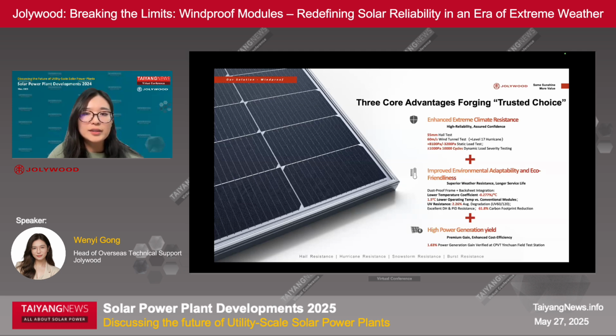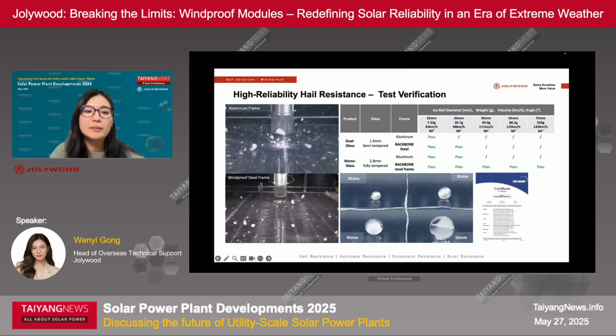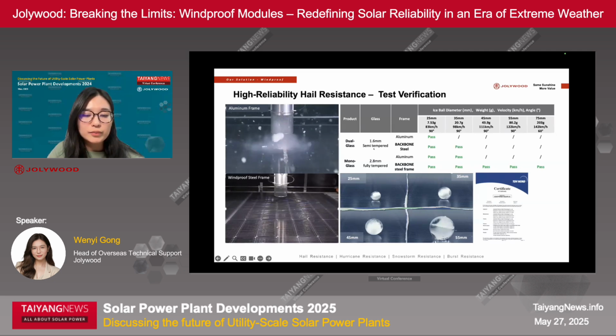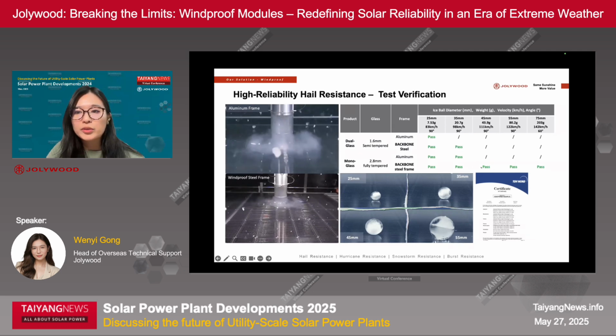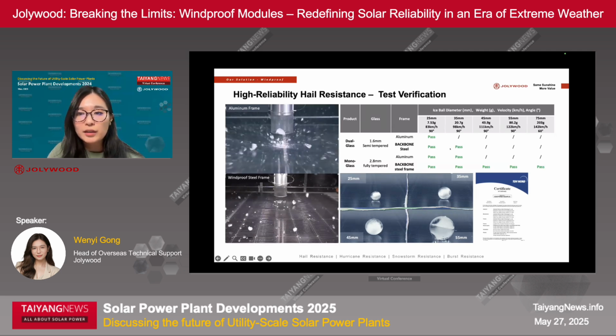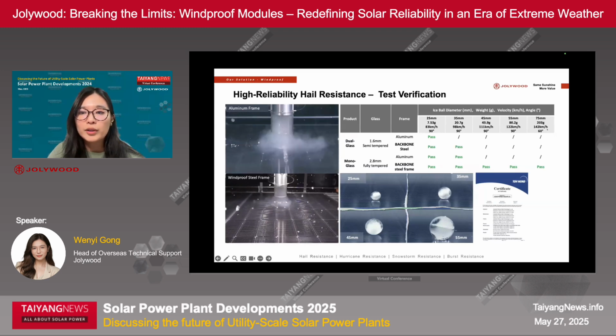Here we can see the hail resistance capability. We performed a verification test between the dual glass with 1.6 millimeter thick glass, and our windproof solution with 2.8 millimeter fully tempered glass, and with different framing solutions. We can see that with the application of the backbone steel frame, the hail resistance can be enhanced, and with the combination of the fully tempered glass, the whole hail resistance can go up to even 75 millimeter diameter ice ball at a certain angle, and at 90 degrees it can withstand a 55 millimeter diameter ice ball.